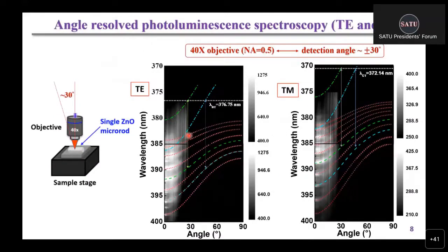However, the prediction actually can tell us the energy dispersion at higher angles. But due to the limitation of the numerical aperture of this objective, we can only collect emissions within about 30 degrees. So in order to confirm the energy dispersion at higher angle, we have to change the method of measurement.